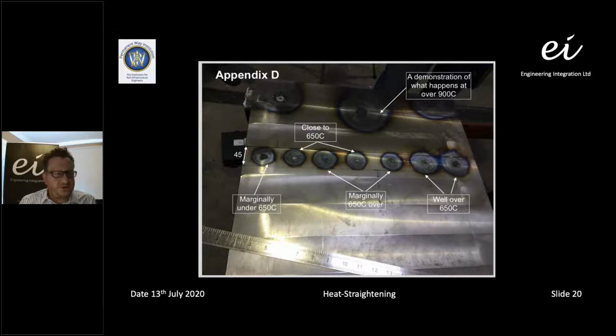What we do during trials, we take a test piece that has similar material properties and thickness to the girder that we're going to be straightening, and undertake heating trials on each element. And we use heating crayons to define the temperature on the test panel. But we don't use heating crayons extensively when we're undertaking the works on site. We utilize the heating patterns that are shown on the steelwork.